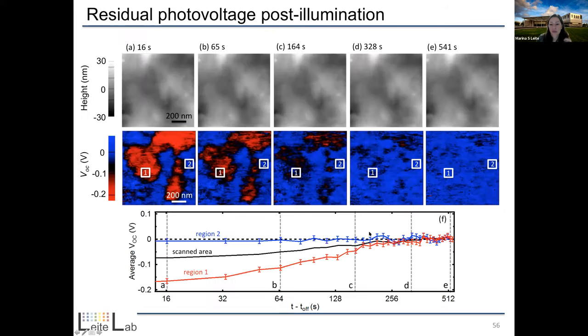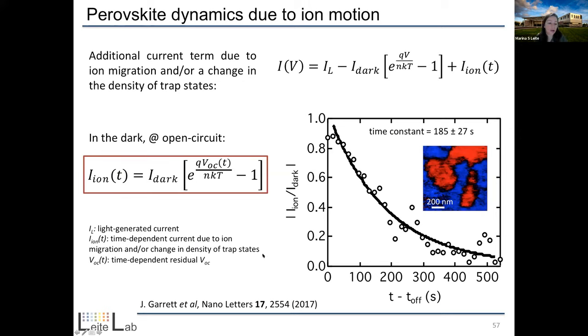I'll skip this slide, here's what's happening. In order to explain the existence of a residual voltage, we essentially have to add a term that corresponds to ionic motion, motion of ions literally within this material. We have to add this term to the diode equation so that it has physical meaning. It turns out this ion motion is something that people have observed prior to our work, I would say in snapshots, before and after illuminating the material.